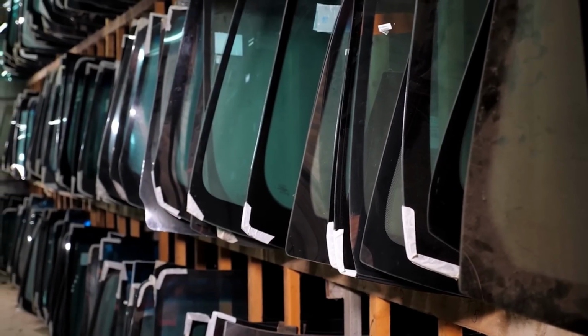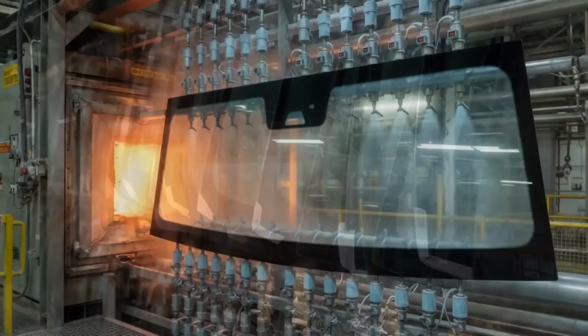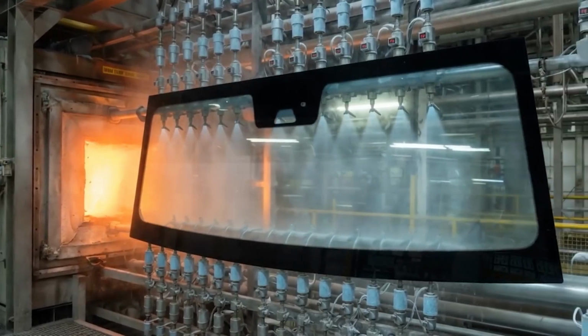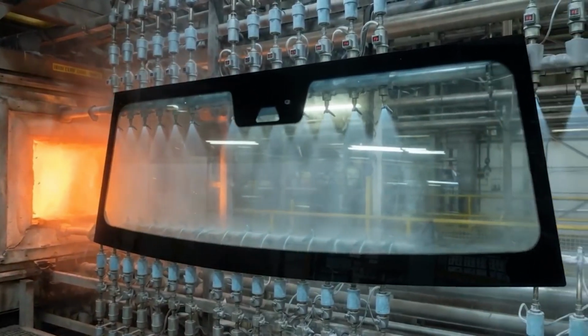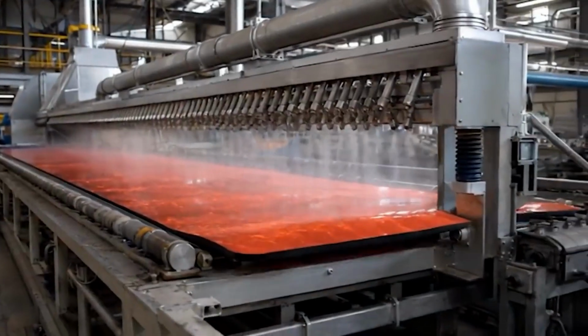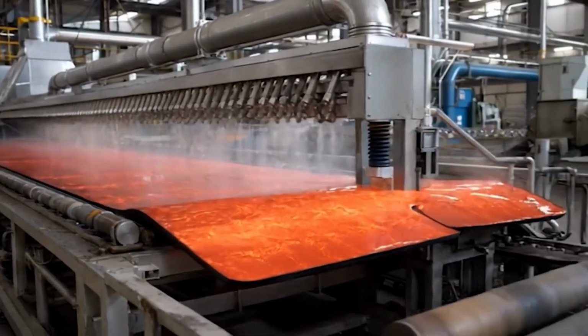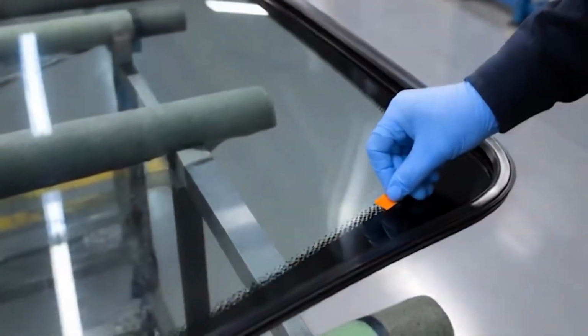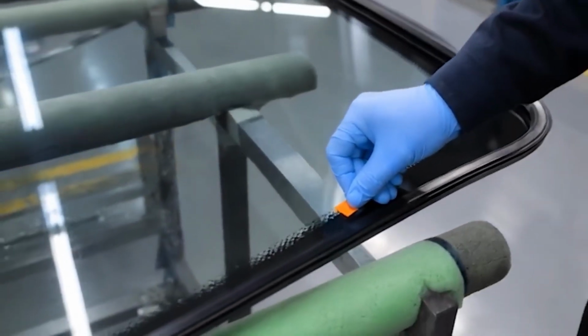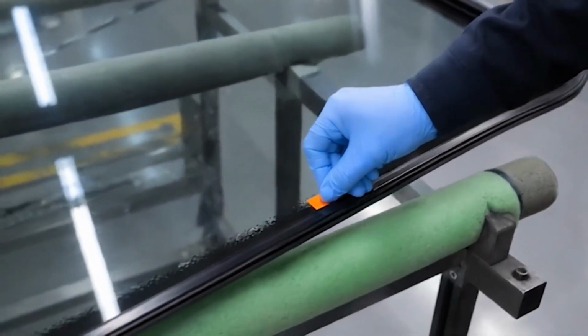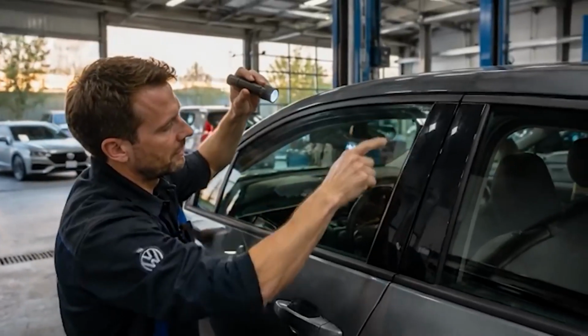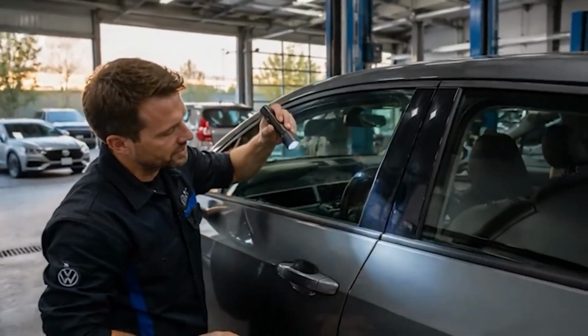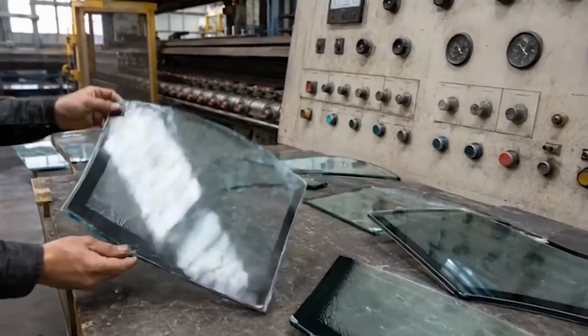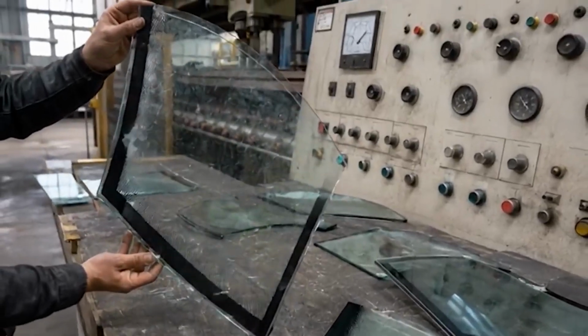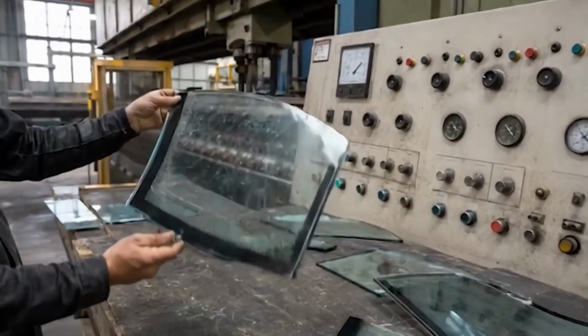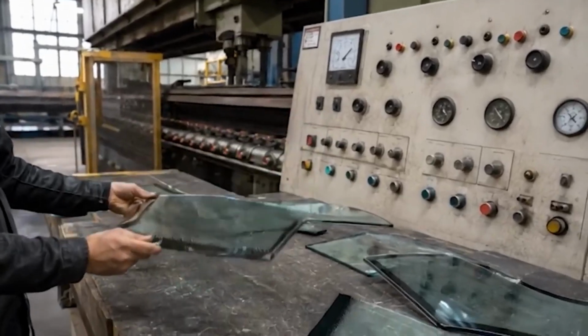The dots aren't decoration. They're a carefully engineered thermal transition zone. Notice how the dots are larger and closer together near the black border. As they move toward the center of the glass, they gradually become smaller and more spread out. This creates a smooth transition between the hot black border and the cooler transparent glass. Instead of a sudden temperature change, heat is distributed gradually. The result? Far less stress, far fewer cracks, a much stronger finished product. The dots are essentially invisible engineering.